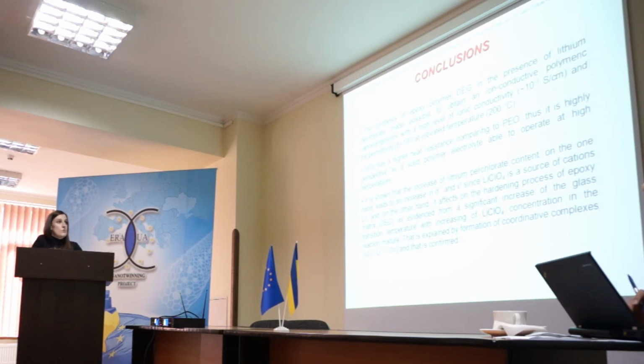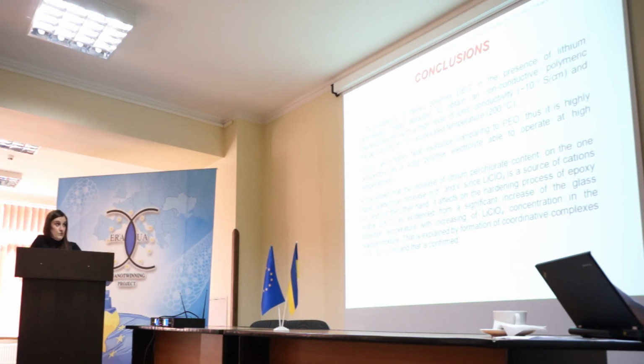The synthesis of epoxy oligomer in the presence of lithium perchlorate made it possible to obtain an ion conductive polymer nanocomposite with a high level of ionic conductivity and permittivity at elevated temperature. It has a higher heat resistance compared to polyethylene oxide, thus it is highly perspective as a solid polymer electrolyte to operate at high temperature.